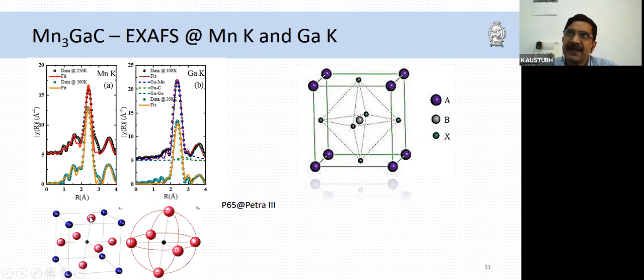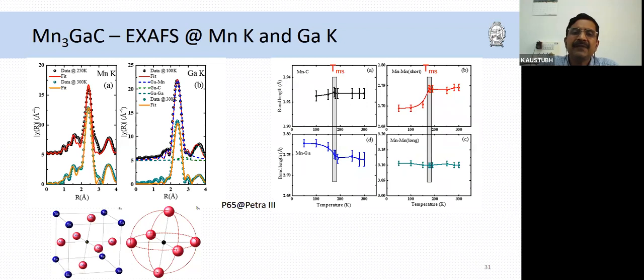And so we conceived a model wherein the manganese octahedra is slightly distorted within the cubic cage of the antiperovskite lattice. We built a model based on this, and we fitted the data, and that data fitted perfectly. And what we got was the variations of the different near neighbor distances. So this is the first nearest neighbor, manganese carbon, across the transition, and not much change in that bond distance